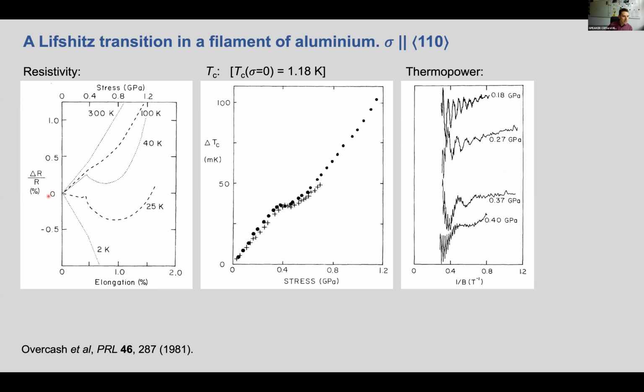So the data on the left show the change in resistance against the elongation of the sample. And they can stretch these samples by almost 2% elastically. And what we see is if they look at 25 Kelvin, there's a little anomaly in the resistivity at an elongation of about 0.5%. The change in the resistivity is small, it's well under 1%, but it's there. And now if they look at TC, the TC of unstressed aluminum is 1.2 Kelvin, and at the same point, an elongation of about 0.5%, there's a little anomaly in TC with a scale of about 20 millikelvin.